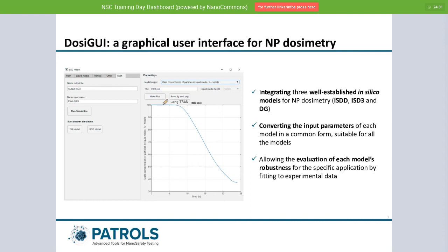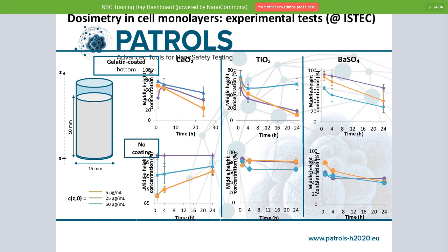Of course, you compare what you get with the data. In the PATROLS Project we have in vitro data for cerium, TiO2, BaSO4 at different concentrations. You can see how this model performed — it performed quite well with the experimental data, for two different types of in vitro setups: the one with a gelatin-coated bottom and the one without coating. The gelatin-coated bottom gives a sticky boundary condition, while no coating applies a no-flux boundary condition. So you identify the most suitable model representing the sedimentation dynamics and test it with the insoluble nanomaterial you have in mind.